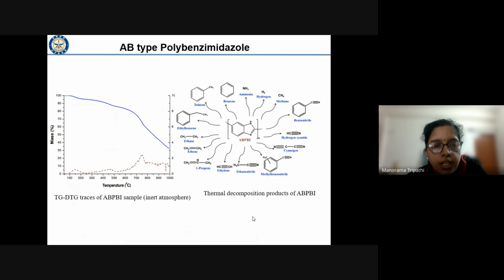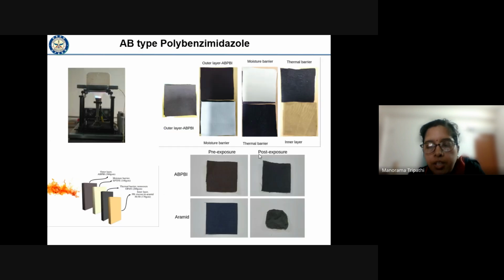So this is the degradation behavior of ABPBI up to around 1000 degrees. It has 30% ash content, which is responsible for its better performance in fire. When we expose to a flame, we have compared ABPBI with aramid, and we have seen that in the case of exposure to flame, ABPBI doesn't shrink much as compared to aramid.